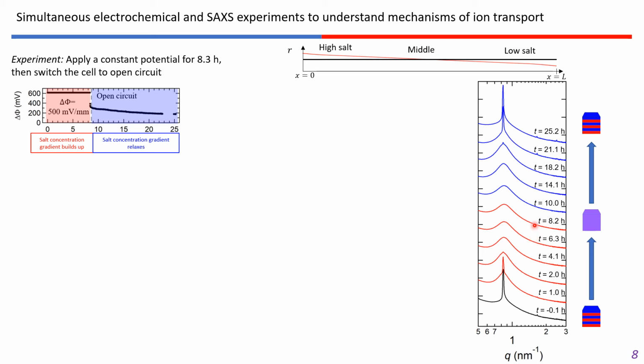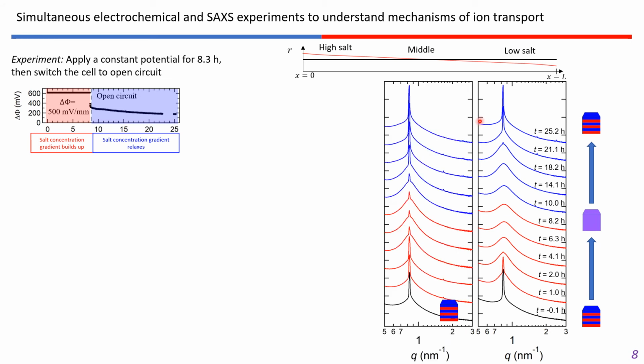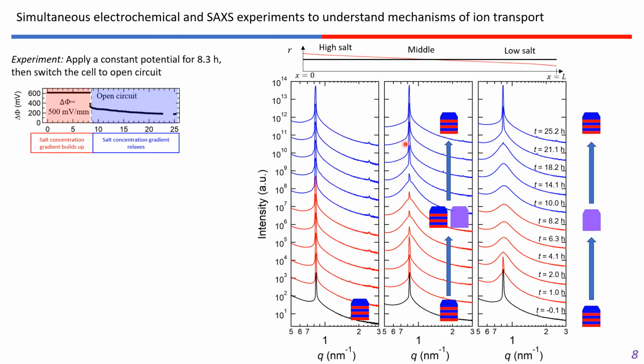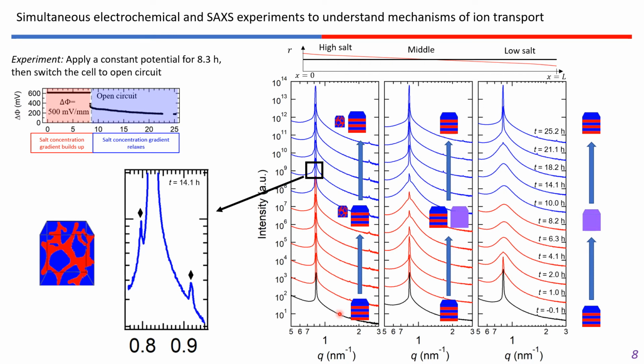When the cell is switched to open circuit and the salt concentration gradient relaxes, we again recover the sharp ordered peak of the lamellar phase. This indicates to us that we do observe morphological changes due to the polarization, and they are reversible. In the middle of the cell, we see a similar behavior. At steady state, we have coexistence of the lamellar and disordered phases, but we again return to the original morphology in the long time limit. The behavior at the salt-rich electrode is more interesting. We expect polarization to result in an increase in salt concentration, and we see the signatures of the lamellar phase throughout the experiment.